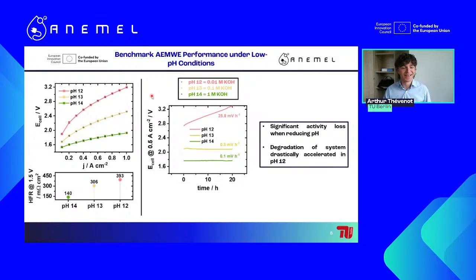Regarding the resistance, we can also see that the ohmic resistance is actually increasing. So of course, there are multiple explanations to it, so it's difficult to really explain precisely why without any additional analytical techniques. But a very possible hypothesis is that as we get scarcer and scarcer in OH-, so in ions in your system, then you have a higher ohmic resistance.